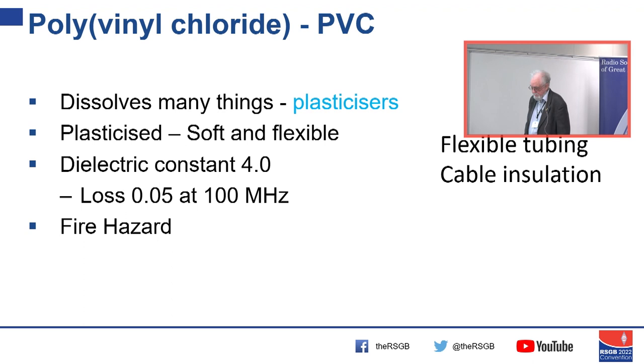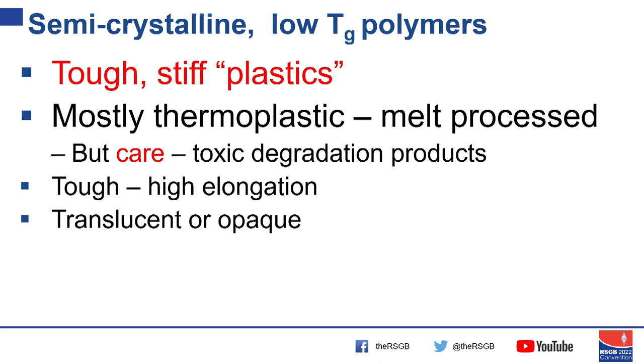So that's an example. What about these semi-crystalline materials? Well, they're tough. Much more tough than the amorphous materials. They're mostly thermoplastics, not always. You can't thermally process cellulose. You do again need to be very, very careful. You generally gain in toughness. These materials will stretch to a great extent without failing, without tearing apart.